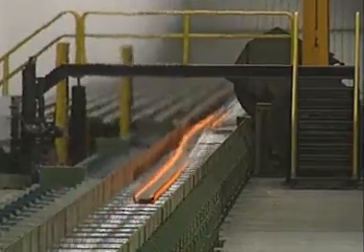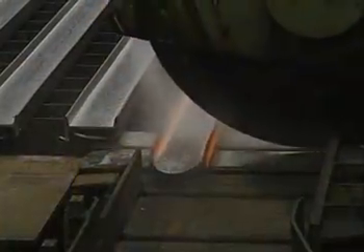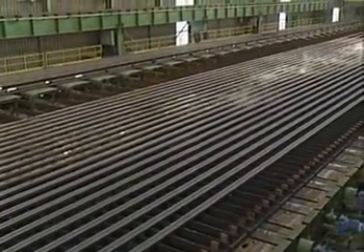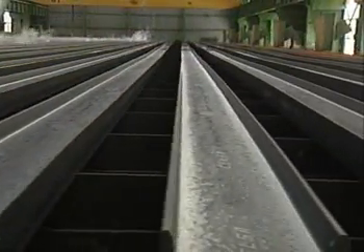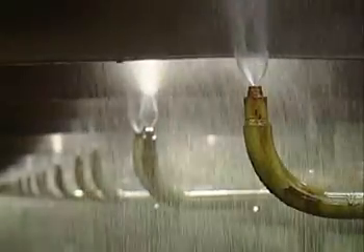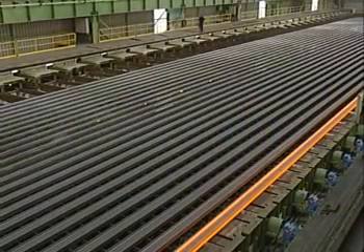The material approaches the finishing end. Upstream of the cooling bed, a pendulum saw is used for cropping and dividing; samples can also be removed here. The walking beam cooling bed is 86 metres in length. An aerosol cooling zone, integrated into the hot section of the cooling bed, allows controlled accelerated cooling of the rolled material — an advantage for plant layout planning, as the cooling area was reduced by 40%.